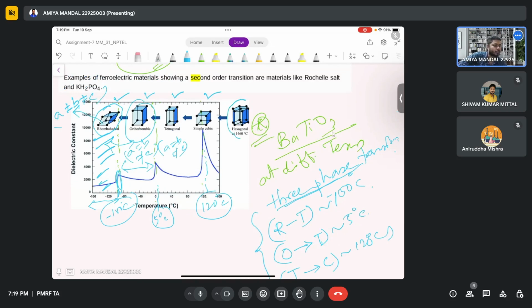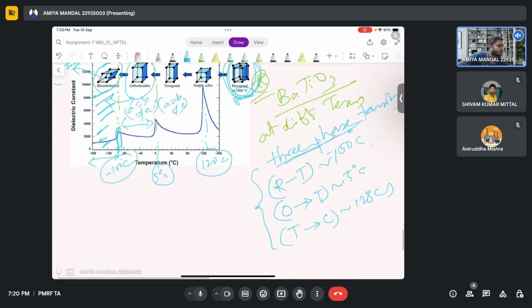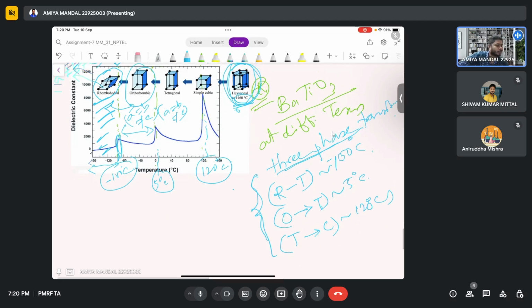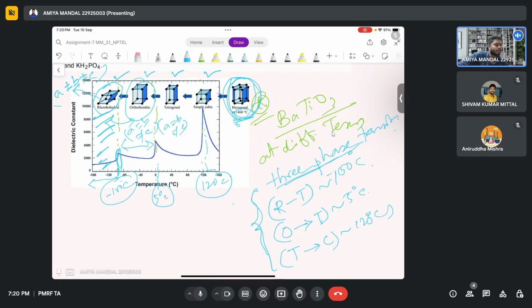And at higher temperatures near about 1460 degrees, hexagonal structures can also be obtained, but these temperatures are not reached in real cases, so we do not observe it in a real case. Some scientists have also observed that. So we are mainly interested in these three regions. Everything tells us how phases change at different temperature regions for barium titanate material. Okay. So how is the dielectric constant varying?